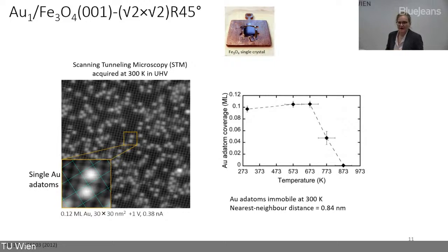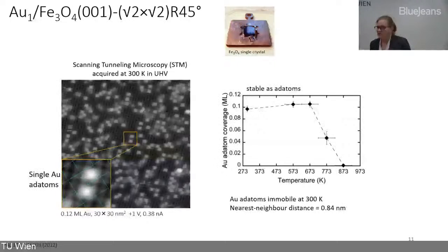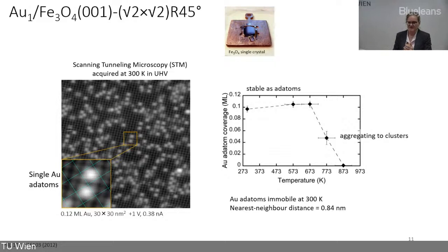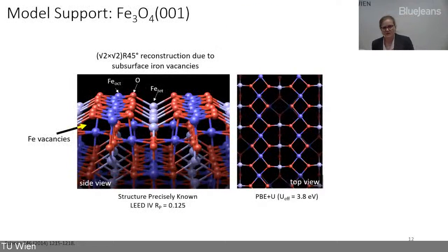And on the right-hand side, you can see the coverage of these gold atoms in monolayers. Not only are they stable at room temperature and don't move at all, they even stay stable up to 673 Kelvin, at which point the density of these gold atoms goes down - not because they evaporate, but just because they aggregate into clusters. So this is the thermodynamically most stable phase. We were really intrigued by this, and it took us another two years to really figure out why.